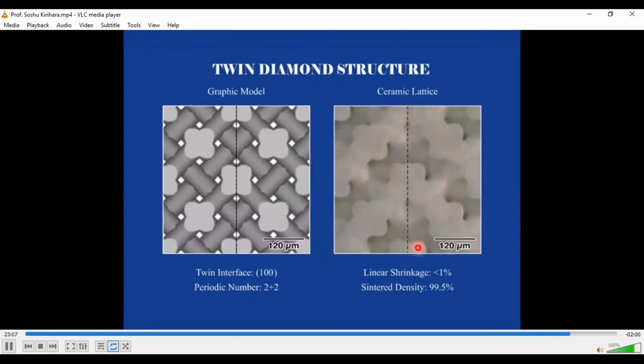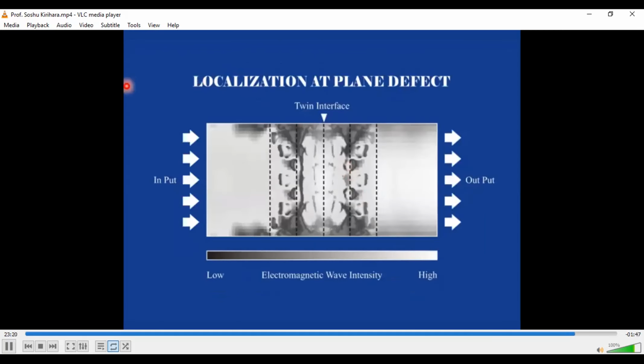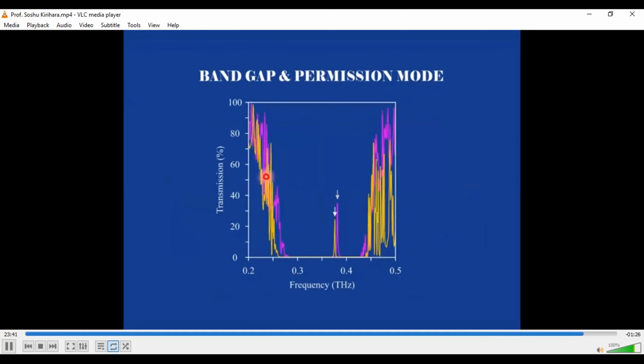This area is possible to localize and resonate electromagnetic waves. In this case, the sintering density reached 99.5%. Okay, this is a localization simulation, and the electromagnetic wave localizes and resonates here, and is reflected by the perfect mirror structures, increasing the power and transmitting to the opposite side. Okay, this figure shows the calculated results and measurement results. Here is a band gap, and here is a localized mode formed by the introduction of the plane defect in the twin diamond crystals. A very clear photonic band gap and localized mode were obtained in both the measurement results and the calculated results.